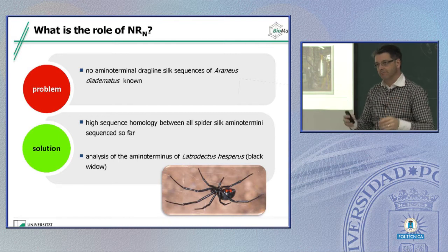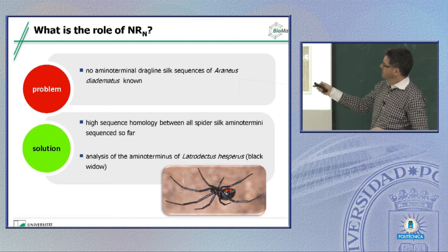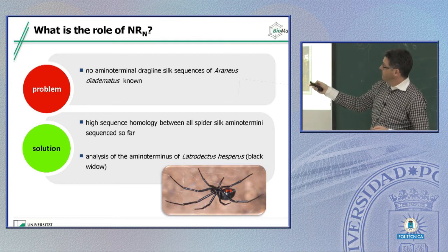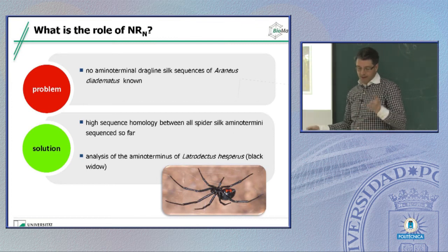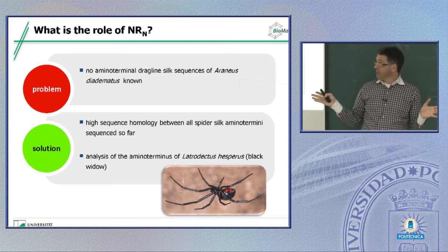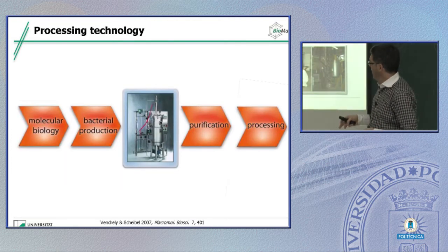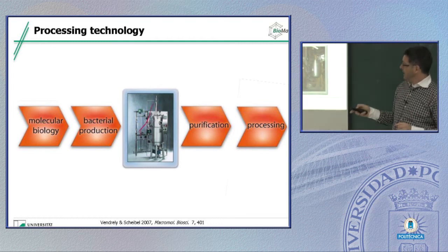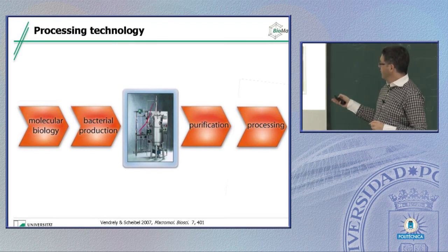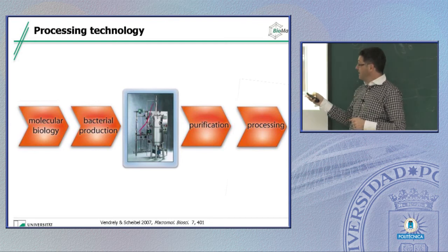If you want to get probably a kilogram, you go to what we call a fermenter. This is made of stainless steel. Here's the biggest one I have at the university, it has 30 liters of volume, so we can make 30 liters of bacterial culture. And out of that we get, if we do it right, between 2 and 3 kilograms of bacteria. However, if you go to larger scales, you get to 100 liters, and this is the lab of the company that we founded. Or you even go to 1 cubic meter, so a 1,000-liter reactor, but this is still the technical stage.